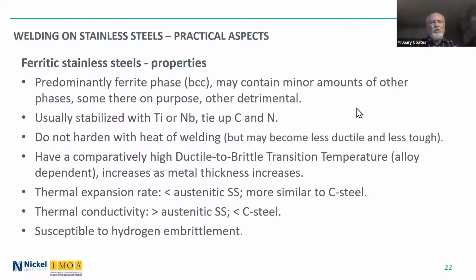So I won't spend too much time on the properties of ferritic, but they're basically a single phase, the ferrite phase. There's often titanium or niobium there to tie up the carbon and nitrogen. Nitrogen can be very detrimental in ferritic stainless steels, so they want to keep the levels down low, and whatever level there could come from welding, you want either titanium or niobium to tie it up.